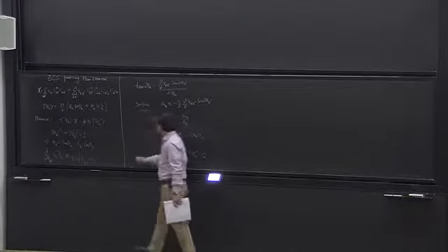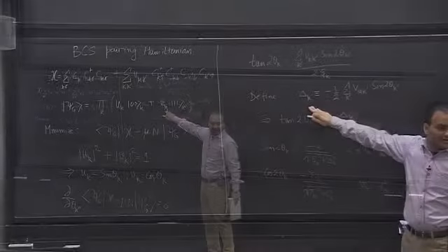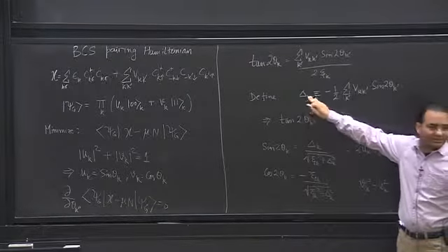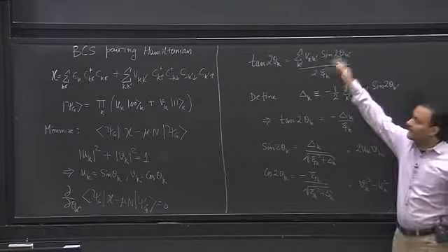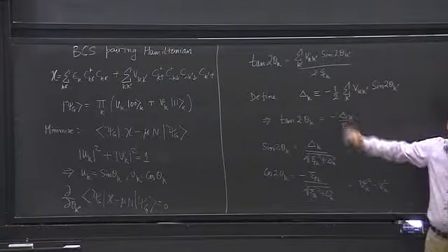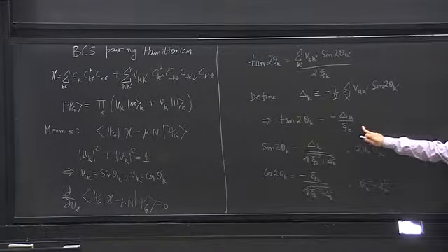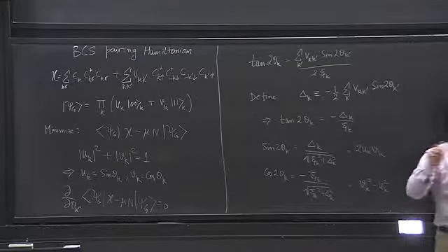So this is the equation that we get when we try to minimize this quantity. Now in this equation, we define a new variable which we call delta of k, and we'll discuss the physical significance of this in a minute. It's defined as basically the numerator times a factor of minus 1/2. So the equation just becomes this. This delta k now includes all the dependence on the potential Vkk prime.